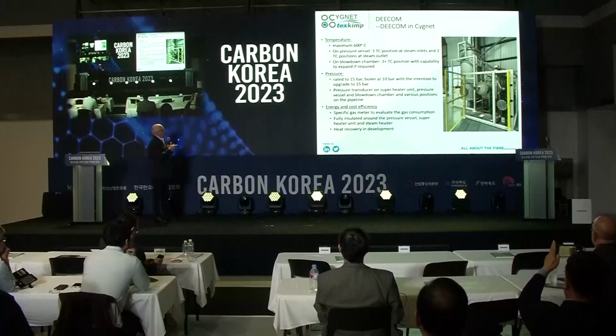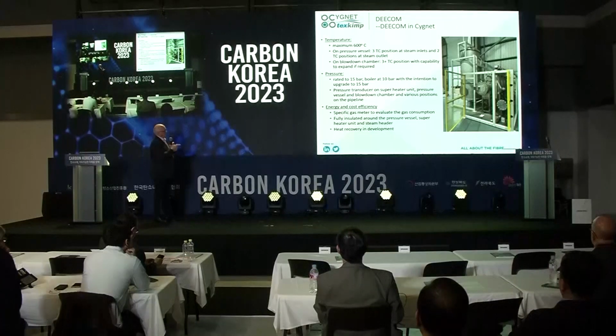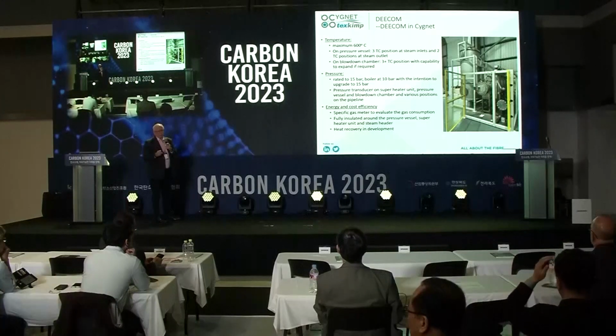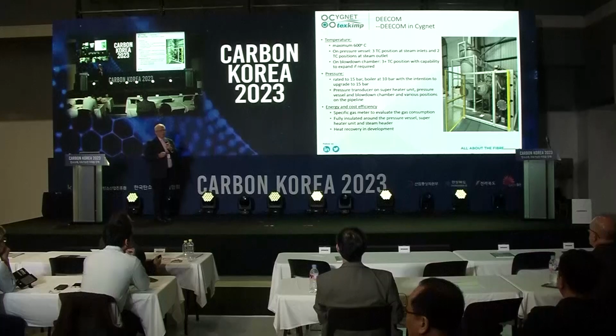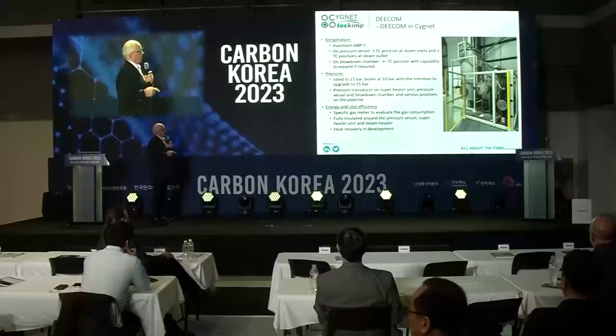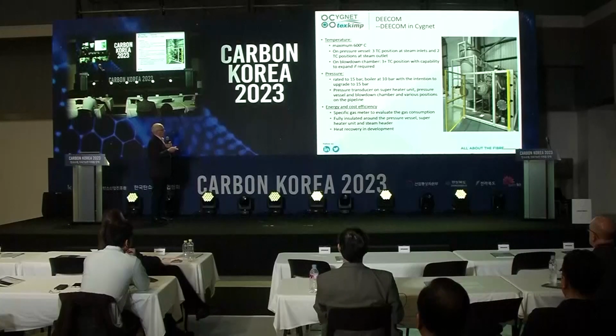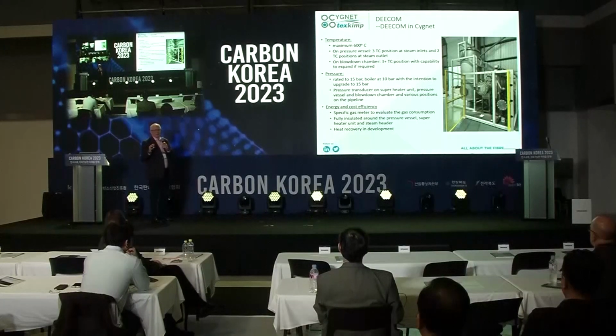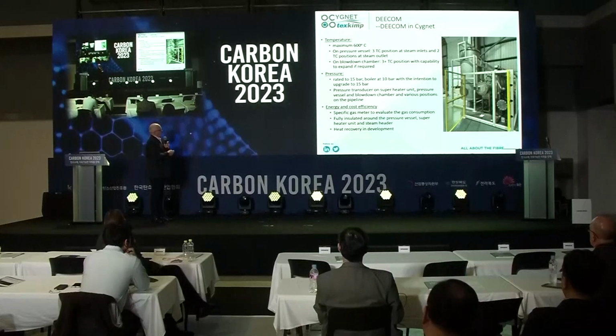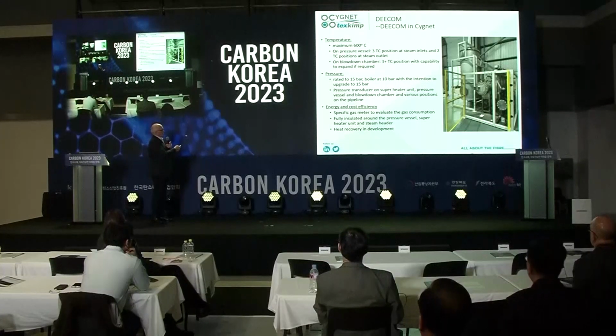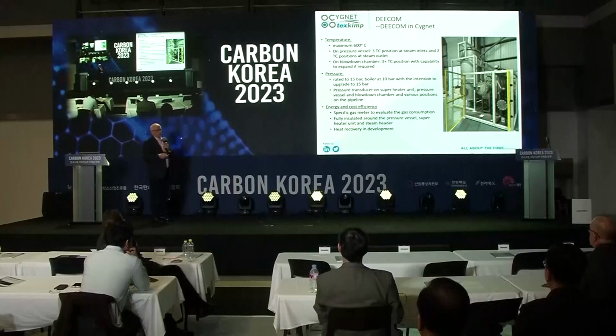The vessel itself is rated to 15 bar, but currently we only have a 10 bar boiler on it, but we fully intend to increase that to a 15 bar boiler. And so it produces, the superheated units also have transducers on them. And so basically, it's bristling with data capture. And what we're looking for, of course, is the energy and cost efficiency based on this.